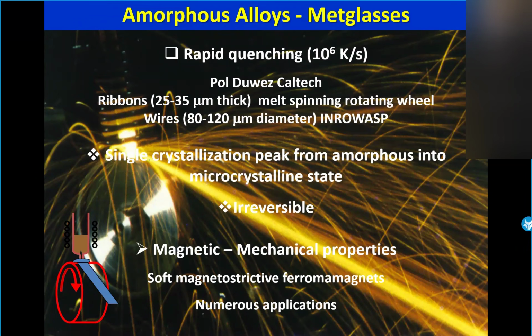So as I mentioned this morning, amorphous magnets, or metallic glasses, were obtained in the 70s. It was following the experiment of Pol Duwez at Caltech. The ribbons typically are between 25 and 35 micrometers when they are obtained by melt spinning on a rotating wheel. Sometimes it is possible also to obtain wires using the in-rotating-water method. That means the wires are not so homogeneous and they are thicker.